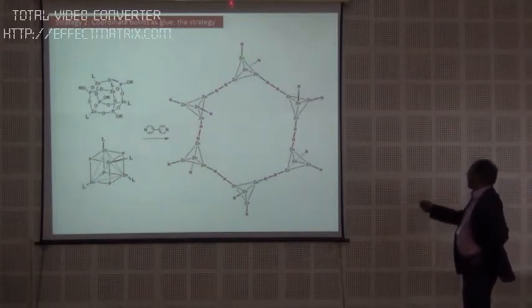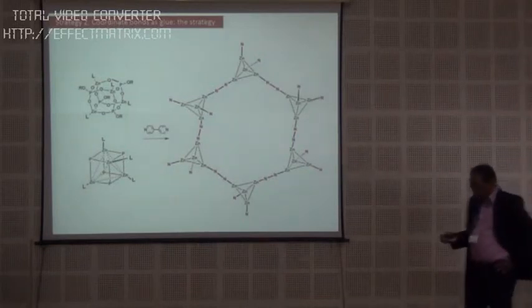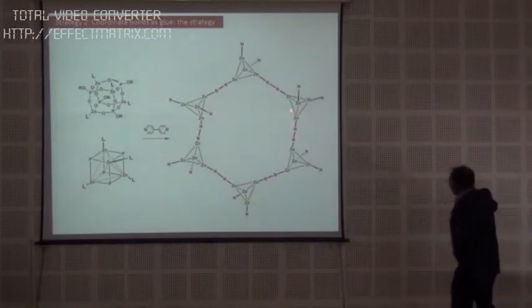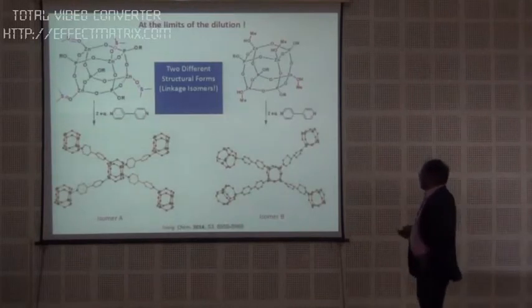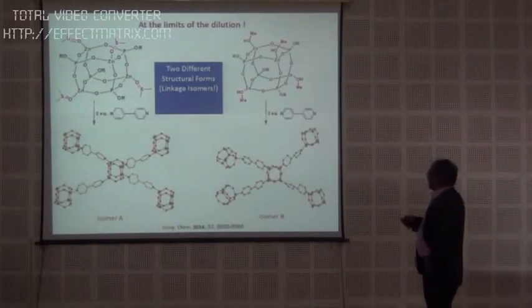this, you can build a super hexagon from which you can actually extend along the X, Y, and Z axis and produce a diamondoid kind of pyramidal structures, which will have nice pores in the order of about 30 to 40 angstroms, depending on what is the separation between the 2 nitrogen atoms in this particular example. Okay, so again we did this a number of examples.